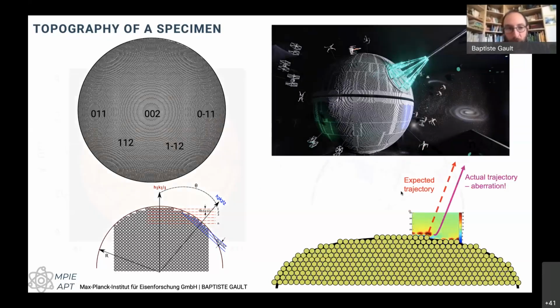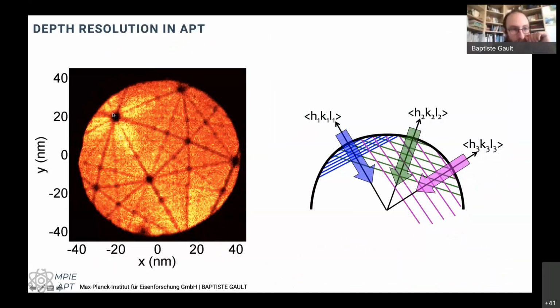For us, it's actually quite good because if I look at this pattern from a pure aluminum specimen, I can determine, based on the symmetries, what set of planes that is, and what set of planes that is, and what set of planes that is. And I'll be able to image these atomic planes right where they are across the field of view. So now I can see these different sets of planes. I can interrogate the data along these different directions to look at whether I can actually image planes, which ones they are, and I can measure the distance between the planes.